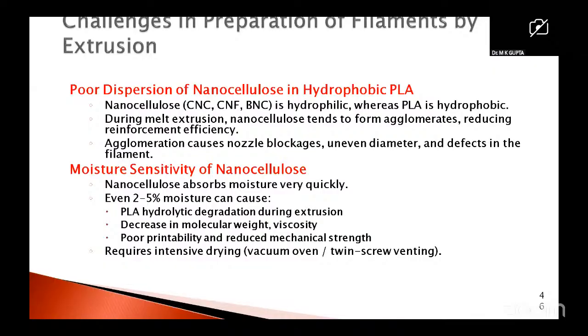Even 2 to 5% moisture can cause PLA hydrolytic degradation during the extrusion, decrease in the molecular weight and the viscosity, poor printability, and reduced mechanical strength. So we should try to avoid the water absorption by the nanocellulose.